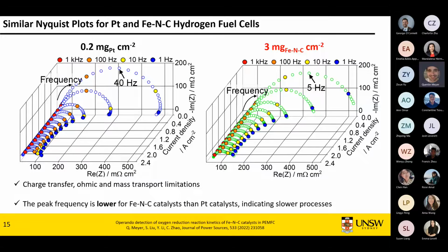So now we took our catalyst and we scanned them with impedance spectroscopy, and we get these kind of weird, pretty 3D graphs. The way they look is, here you've got very high charge transfer resistance, then you have an ohmic region, and then some sort of mass transport limitations, but very minimal, happening at low frequencies. When you look at platinum and Fe-N-C, the catalyst impedance results are actually fairly similar to each other. What you've got in between the two is overall the same kind: charge transfer, mass transport, and ohmic. But one thing you can see right away, if you look at the frequency of the peak, it's about 40 Hertz in one case and about 5 Hertz in the other case.